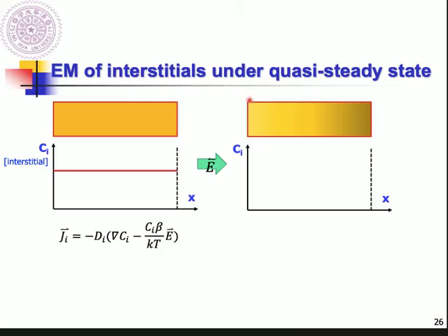So you try to plot the potential versus the location. You can get this direction, right? It's a cathode, it's an anode, and due to this electrical field, you can write down the direction of the electron flow. This electron flow is going to push the atoms to move toward the right-hand side. So the concentration profile of these interstitial atoms will become like this, because the electrons push the atoms toward the right-hand side.